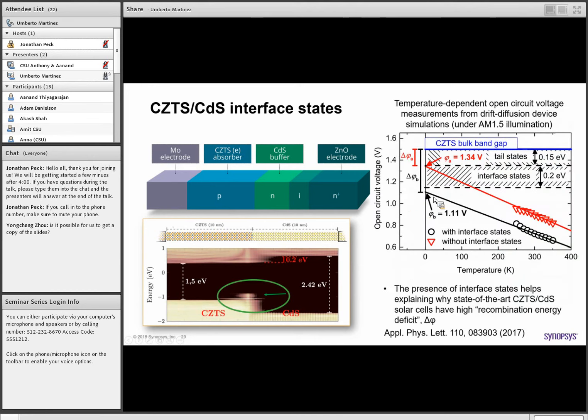And if we go even further, we study the temperature-dependent open circuit voltage measurement from this type of simulations with and without these interface states. We can calculate this recombination energy deficit, which we couldn't explain, as it was so high, without introducing these interface states here.